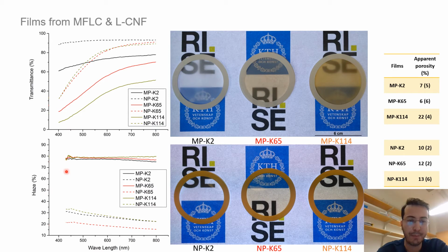And here you see that the haze of micropapers is quite high, about 80%, and for the nanopapers it is much lower. So haze or cloudiness is much higher for the micropapers because we have larger and wider fibrils, and these are scattering sites which scatter light. Still, light is getting transmitted to a quite high extent, as we can see in the transmittance, but at larger angles, which makes them cloudy.